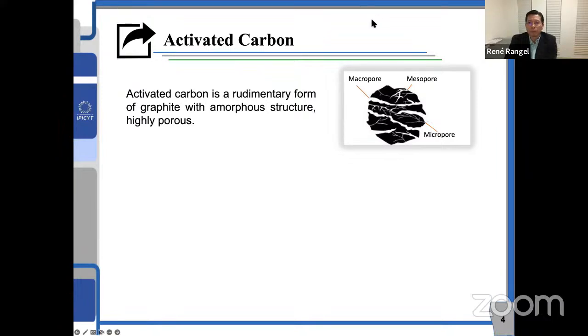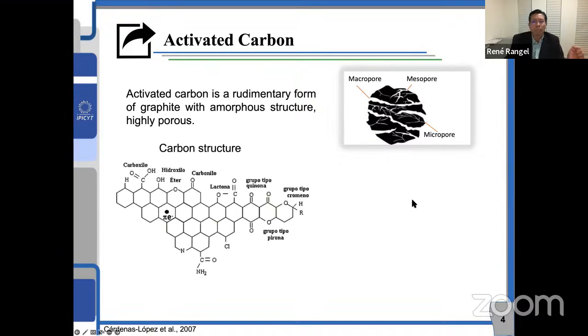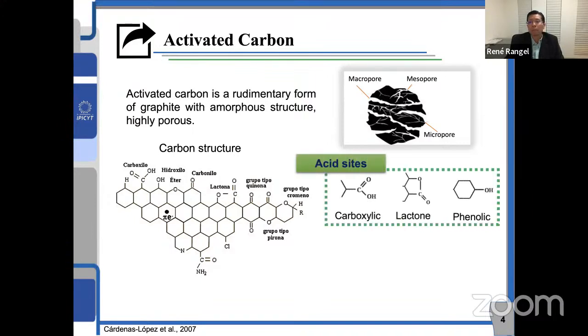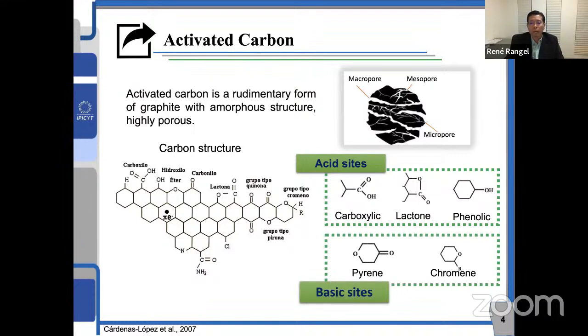As I said, I will give you a general introduction about carbon materials. Some of you already know that carbon materials is an amorphous structure, made of graphitic layers. This material is highly porous, has different size of openings that are named as micro, meso, macropores. And also this material, of course, is made of graphitic layers that are decorated with some groups, usually oxygen-containing groups. Within these, we have the acidic groups like carboxylic, lactonic, and phenolic that usually will give you a negative charge depending on the solution pH. Also, we will have basic sites like pyrone and chromene that usually will give you a positive charge.